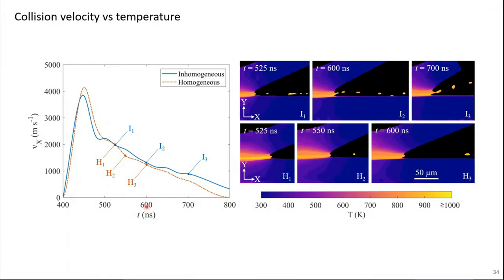Now the area under the velocity-time curve, if you integrate it, will give you the distance. So it also shows you the amount of weld that is being formed. The area under the blue curve is actually substantially greater than the area under the orange curve. So you actually get a larger weld zone when you include the effects of microstructure. To give you an idea of jetting, what we've done is we've extracted a few different time frames. I couldn't extract the exact same time frame, just given that the homogeneous model didn't really have that much jetting in comparison to the inhomogeneous modeling, where you see so much volume of jetted material coming out of the mouth of the weld.